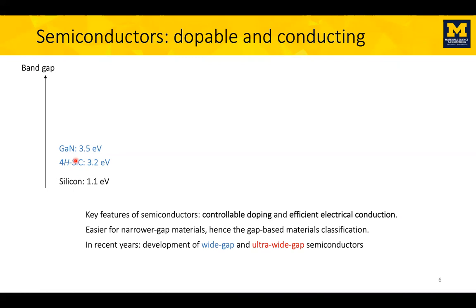So you need to make your silicon chips thicker and bigger. And when you make them bigger, they act like big resistors. Nevertheless, they're still cheaper than these fancier materials. So for example, if you buy an electric car, there are lots of chips around to control the flow of electricity from the batteries to the motors, but they're still based on silicon. Only Tesla uses silicon carbide, because it adds about $100 to the cost of the car to replace the silicon electronics with silicon carbide.